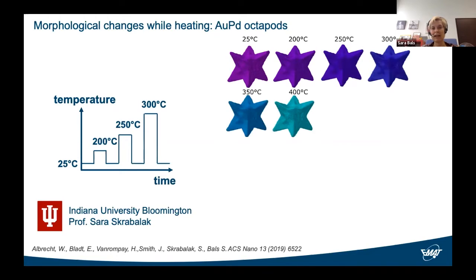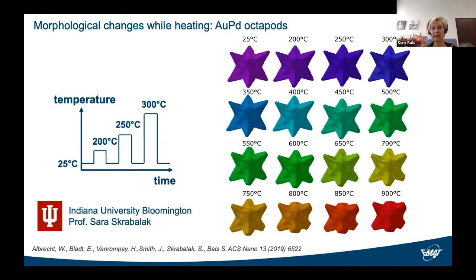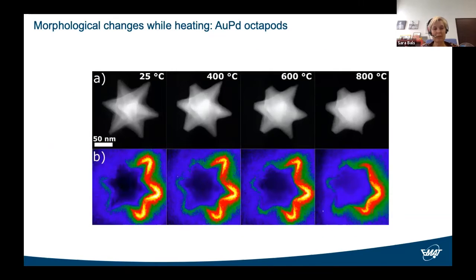and so on. And again, because we can capture the tilt series in a few minutes, we can repeat the process multiple times, and we can map now what is happening as a function of heating temperature. We can again see that the sharp tips are disappearing. They become blunt, and again, that will influence their properties. As we can see here, for example, through these plasmon maps, where we see that the intensity in the plasmon maps decreases, and that is simply because the sharp tips become blunt.